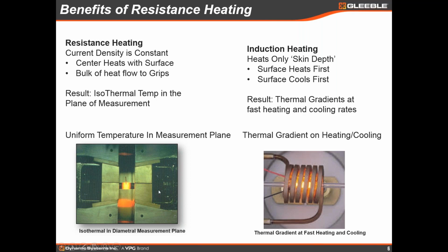So what we get with the Gleeble, since we're using direct resistance heating, we're using a current to heat it, and that current has an equal current density on the surface of the sample as well as in the center of the sample. That means that no matter how large my sample is, 10 millimeters diameter, 15 millimeters diameter, I am heating the point of material at the center of that sample at the same rate that I'm heating a point of material on the surface of the sample. Since that current density is constant, I'm able to heat the center, the mid diameter, and the surface of the sample at the same rate. So the important part of that is that I get an isothermal plane across this diametral plane of the sample. I don't have a hot spot on the surface while I have to wait for the center to heat up and get hot.